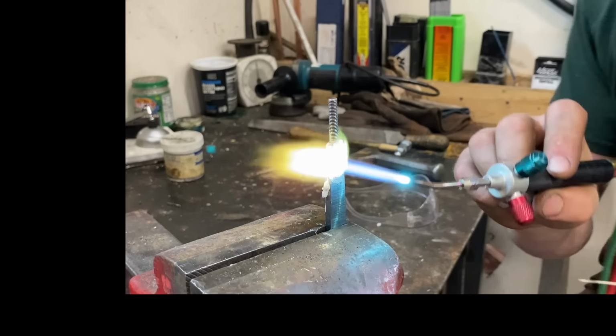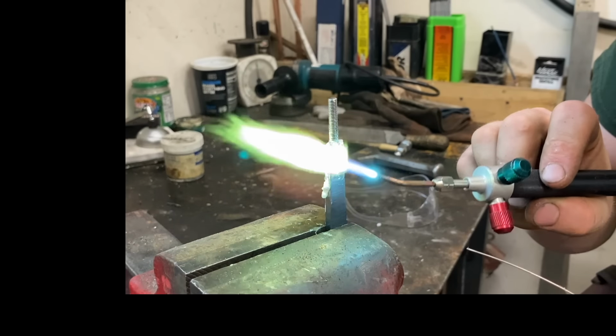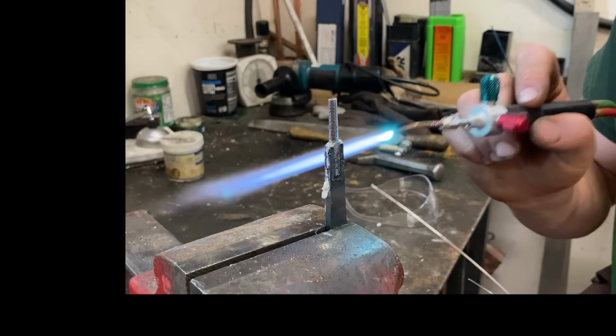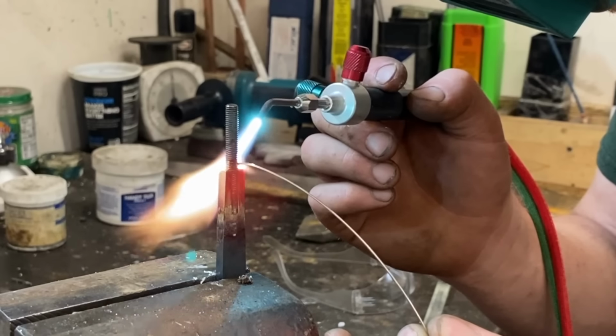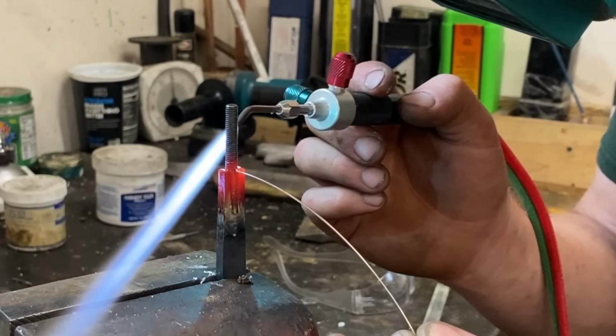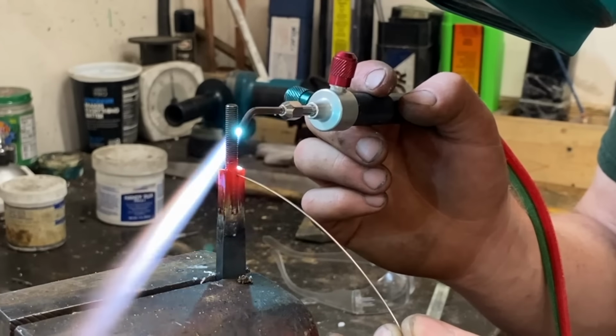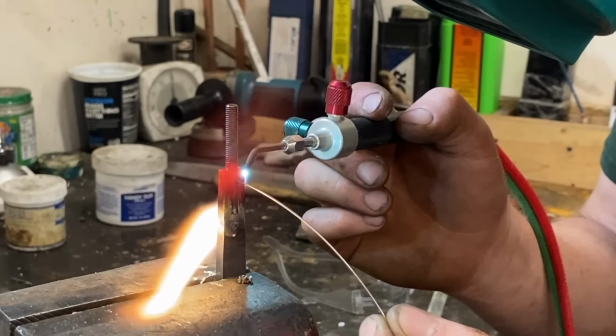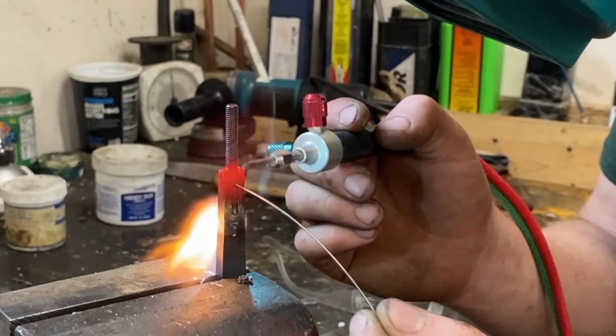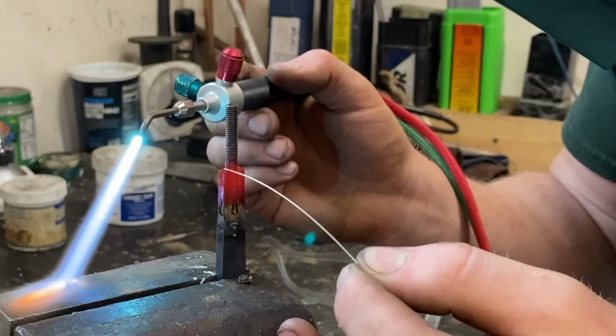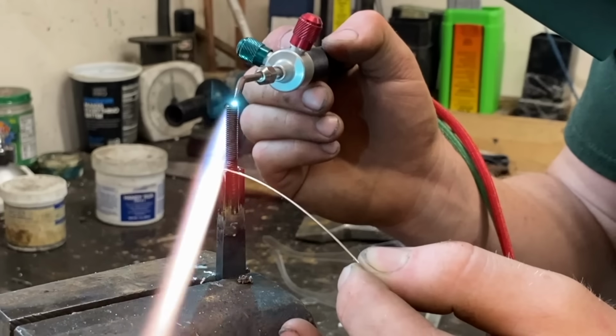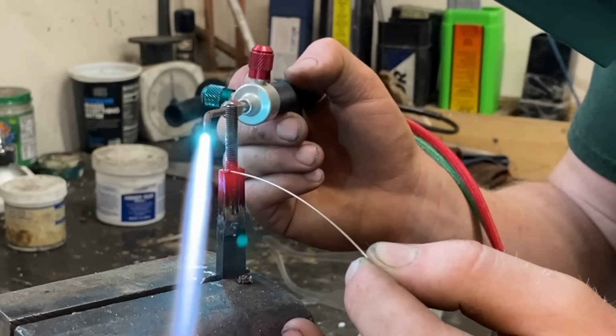There are a number of reasons why I prefer silver brazing to welding for attaching threads to a tang. Not only is it easier to redo if I mess something up, it also helps to avoid the issues of grain growth and warpage, which are both very common in welding, which would leave the tang misaligned and/or brittle. Plus, it's just satisfying to watch the silver brazing wire melt and flow into the joint.